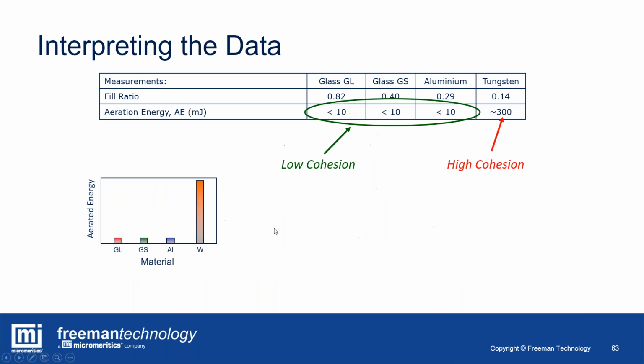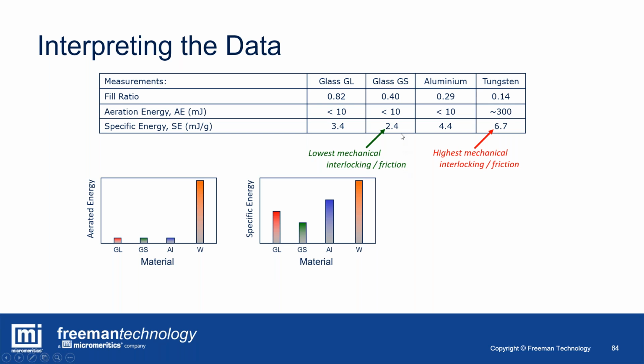So what we're saying from that data is that for 3 materials we had low cohesion, for 1 material we had high cohesion, as defined by the aeration characteristics. From the specific energy, we can see that we've got the lowest mechanical interlocking for the small glass beads and the highest for the tungsten. And yet, as I said a moment ago, the flow properties of this material seem to be the best, but the process ranking is not the best. And in fact, it performs half as well as the large glass beads. And the question is, what's the rationale for that?